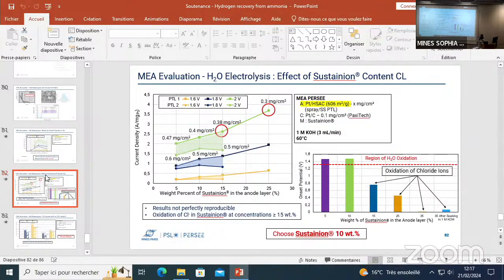I think we have a problem of catalyst for the moment, because the huge recovery wouldn't take us to industrial applications where we need to shut down our electrolysis cell every 3 hours to reactivate the catalyst. So mainly we should work on the catalyst. In my opinion, after all these tests, specifically when I evaluated the homemade catalyst with different active phases, the next step would be to work on the catalyst support, in order to find an optimum pore size. I think it could be the solution for the recovery time.